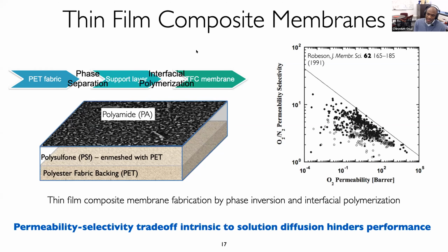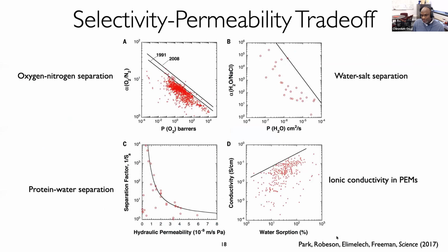Now, the transport regulating features in thin film composite membranes are, of course, the polyamide network that's formed by interfacial polymerization. Nevertheless, even at that very small length scale, the heterogeneity in the network structure gives rise to selectivity permeability trade-offs that are also seen in reverse osmosis desalination. Okay, and this idea of a selectivity permeability trade-off also shows up in other contexts. Here, this is the famous Robeson plot for gas permeability, a very nice paper by Elimelech, Benny Freeman, and others, and Robeson also highlighted the existence of the selectivity permeability trade-off in a variety of other separations.